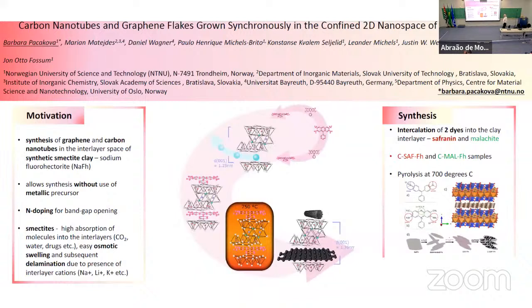One is synthesis of graphene. What we have done, we have taken these clay stacks. Into there, we have put dye molecules, safranin or malachite. Then we heat this up to 700 degrees and out comes graphene inside there. So we synthesize graphene inside there at much lower temperatures than bulk synthesis of graphene. So the low temperature issue is important here.